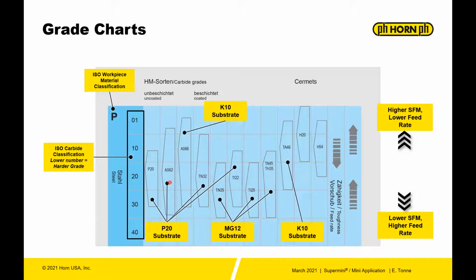But you have an AS62, a TN32, a TI22. Those all use the same grade of carbide. What you will notice though is that based on the coating system, the coating system actually makes the grade. The carbide substrate, it can improve the toughness or the hardness of that and the range of that hardness. So you'll see that a P20 ranges between a 10 and a 30 with respect to toughness. But then if you put an AS60 or an AS coating on it, it ranges from looks like a 5 all the way to a 35. So it's not only substrate, the coating does also add some properties to the grade.